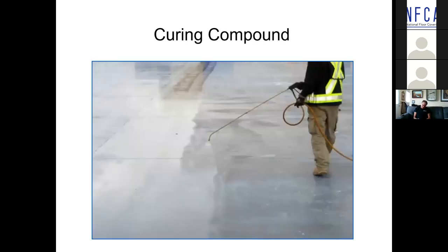Curing compounds. When I grew up in this business 45 years ago or more, curing compounds were the norm, particularly membrane forming curing compounds. Why? Very inexpensive, very easy to apply, accomplish the curing. However, the ASTM standard F710, standard practice for preparing concrete subfloors to receive resilient floor coverings, doesn't say not to use one, but it does say it's got to be removed, and it's very costly to remove. Now, there is a class of curing compounds referred to as dissipating, but they don't just break down overnight. It takes ultraviolet light, takes abrasion. It could take 60 to 90 days for it actually to break down.